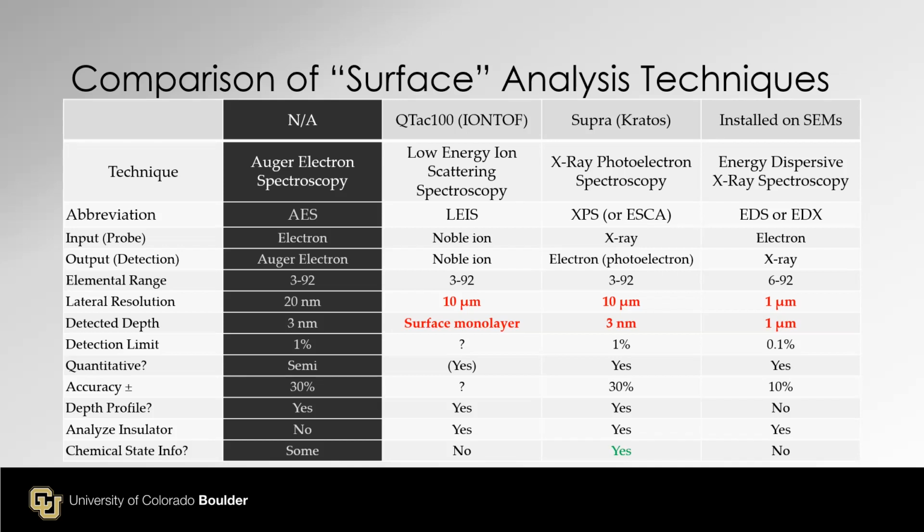Quantitative, yes. For the aluminum K-alpha line input X-ray, a good database has been established, so we can frequently perform standardless quantitative analysis. Accuracy, depending on what the situation is, but 30%. I don't recall who said 30%, but somebody said so.